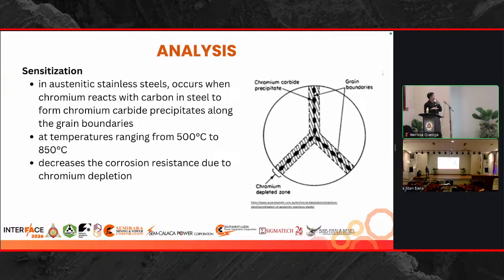But when sensitization occurs, the chromium available for passivation gets depleted because it gets sensitized within the grain boundaries of the microstructure. So it will produce a chromium depleted zone, and thus it reduces the corrosion resistance of our sample. So this is also an important microstructure degradation feature to look for in high temperature members.